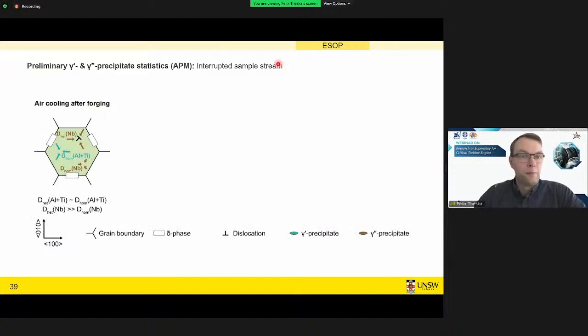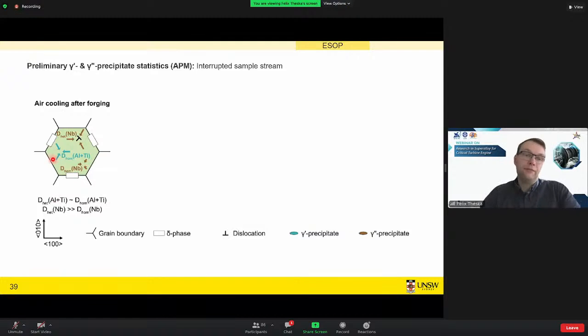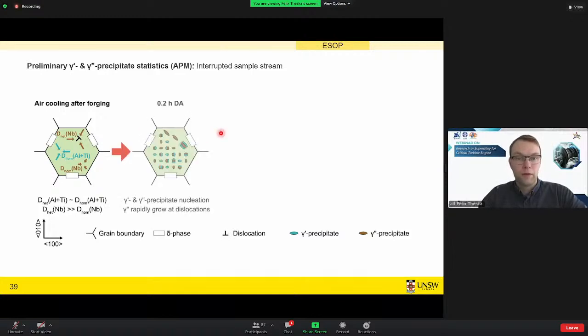Okay. Now we can adapt our microstructural model even further. We start with the air cooling after the forging, where along these dislocations, we have a high attraction of niobium, whereas aluminum and titanium, in this study, we have not observed a similar trend. Okay, so at least for niobium, the diffusivity along dislocations seems to be greatly accelerated. What this means is we have these gamma double prime particles forming along the dislocations and then growing quite rapidly, whereas the population of smaller particles, they grow much slower within the matrix.